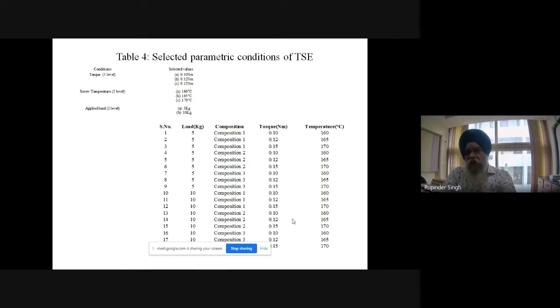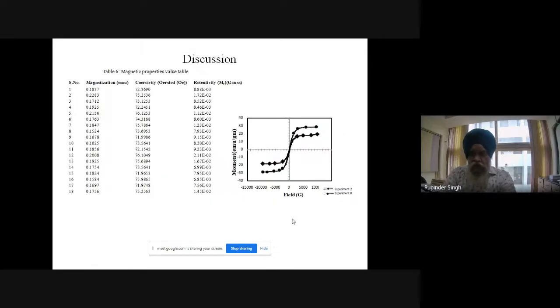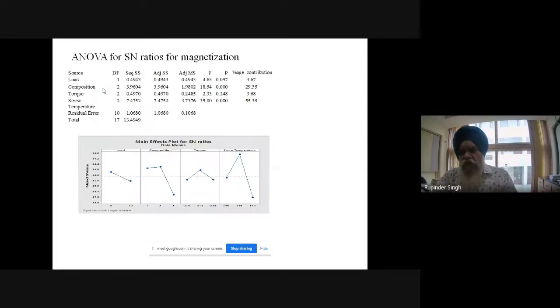We used it on an extruder and tried to optimize some of the parameters, and we tried to see their magnetic properties, the typical BH curves. We are interested in their magnetization. Magnetization means how easily I can magnetize that material. Then coercivity, right? If I am interested in making the effect of the magnetic field zero, then in the opposite direction I have to apply the magnetic field, right? So how much in the opposite direction do I have to apply the magnetic field? So we measure the coercivity, and once I switch off the magnetic field, how much magnetic effect will be there? That is in terms of the retentivity. So we try to measure this for this type of combination of material.